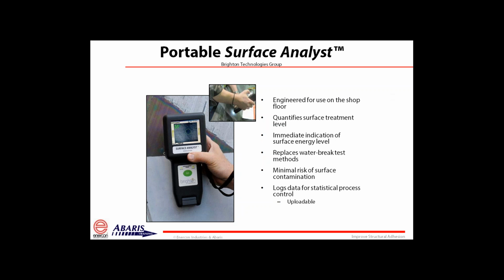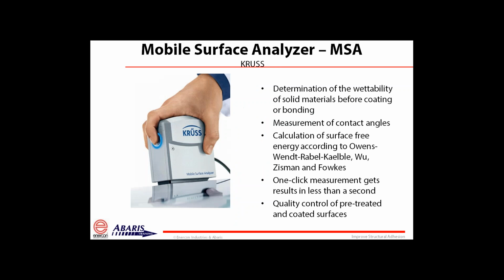What it doesn't do is give you the calculation for the actual surface free energy measurement. For a tool that does that, you would look to something like this, the Mobile Surface Analyzer by Kruss. This one will also determine the wettability through the measurement of contact angles and calculate the surface free energy in accordance with the Owens-Wendt, Rabel, Kaelble, Wu, Zisman, and Fowkes methods. So that standard is basically the calculation for the surface free energy value. You'll see later in Ryan's presentation some of the calculations that are made using this equipment. It also allows for one-click measurement and gets results in less than 1 second, like the previous equipment. The only addition is that it gives you more information.